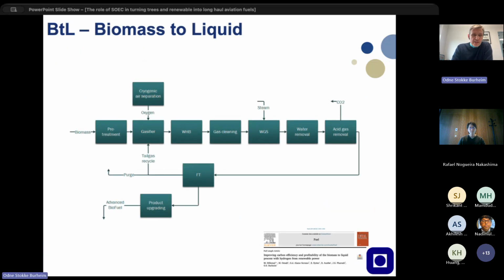The BTL process, as I mentioned, starts with biomass coming in, envisioned as forestry waste essentially. It has a pre-treatment, which is essentially drying. It goes through an entrained gasifier, where wood chips together with pure oxygen under stoichiometry creates a syngas that then goes for a bit of cleaning.